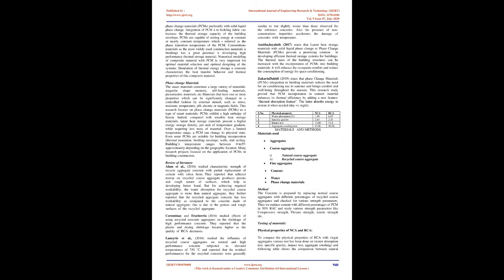The objective of present study is to determine the sustainability of RCA as an alternate material to NCA and PCM to cement and to compare the compressive strength. The tests were conducted by replacing the coarse aggregates in concrete mix of M25, 1:1.61:2.74. The mix designing is done for water cement ratio 0.45. Cubes are casted by replacing NCA aggregate with 0%, 30%, 50%, 70% RCA, and cement with 0%, 10%, 20%, 30% PCM.